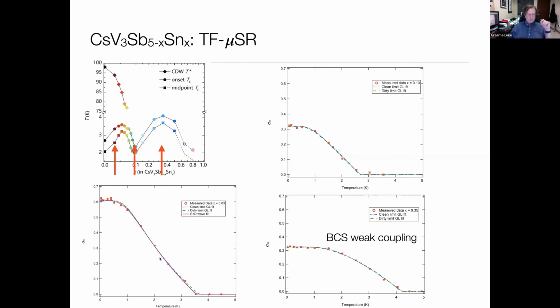So the first thing you see is in the 3% doped sample, the vertical axis, these are all plotted on the same scale. The superfluid density is the highest here. And so as we're doping, we're lowering the superfluid density. We're adding holes, getting rid of net charge carriers in the system, whereas we're moving the Fermi level around. And so in fact, the carrier concentration is changing quite strongly. You see here, you have very strong temperature dependence again to this superfluid density. There's a small slope at low temperatures, and it's changing strongly over a wide temperature range. The slope changes over a much wider temperature range than in BCS theory.